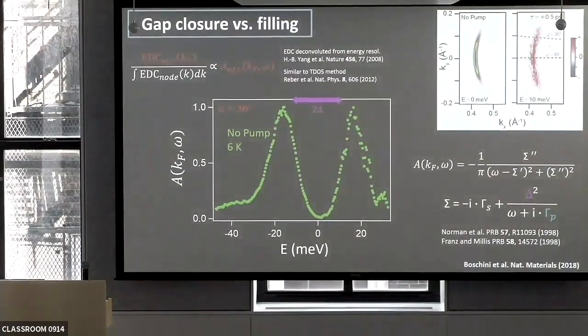The experiment looks already surprising to some degree, even without a pump. So here is the binding energy. Here is the temperature, 6 Kelvin. This is your Bi2212 sample. These data are measured along the node. Sorry, close to the node. Here you can see the Fermi surface of this cuprate. So you have nodal data, and here they are measured just away from the node. So the gap is large enough. It's not the largest gap, which you find at pi, 0, but it's large enough to be observed.